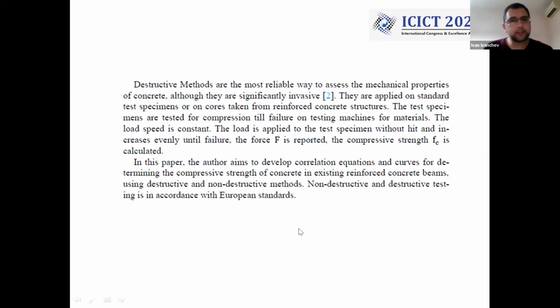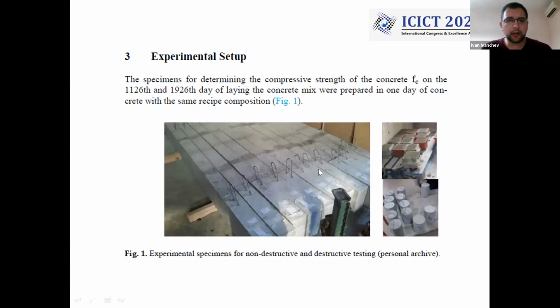The fourth method is the destructive method, the most reliable one, but it has a very adverse effect on the buildings. They are the most accurate, but the negative thing here is that we make a violation on the buildings, on the members, and sometimes we make failures inside them, which are not easy to be repaired. So some few words about the experimental setup. On figure 1, you could see the test specimens which were used. You can see the 12 reinforced concrete beams, the cubes and the cylindrical cores which were drilled from the beams.